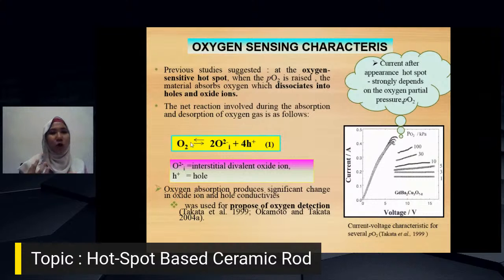Next, we are going to the oxygen sensing characteristic. It's very important when talking about oxygen sensing. We need to see the characteristic, how they can perform as an oxygen sensor when you change the concentration of the oxygen in the surroundings. The previous study suggested that at the oxygen sensitive hotspot, when the oxygen partial pressure is raised, the material absorbs oxygen which dissociates into holes and oxide ions.